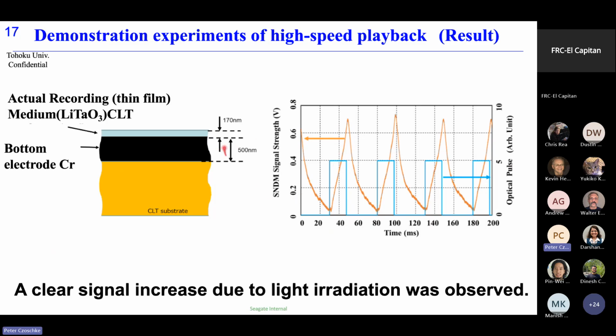And this is a fundamental investigation result. This blue line is a waveform of the applied optical pulse. And this orange line is the SNDM output signal. So by the optical pulse irradiation, a clear increase of the nonlinear dielectric response was observed. But unfortunately, due to the restriction of the laser and the other equipment at the time, the response was very slow, in the millisecond order.